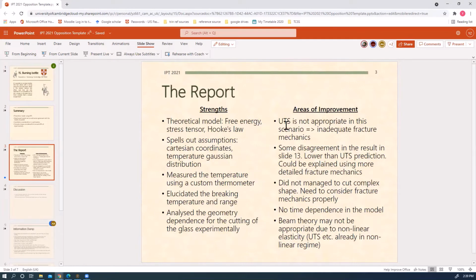And as a very quick example, we can think of things like reinforced glass. The glass is reinforced by introducing a compressive stress on the surface to prevent those cracks coming up. And just by this surface treatment, the ultimate tensile strength can be increased by probably at least one order of magnitude, I think. I agree on that.